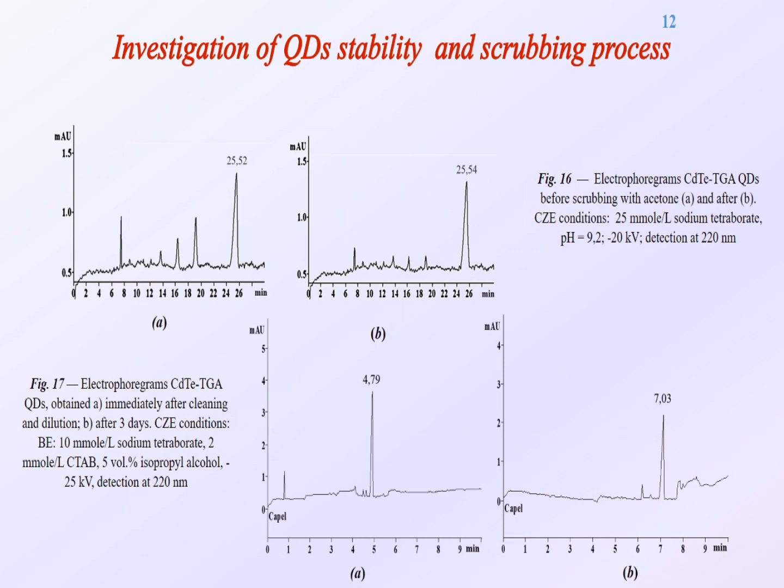Capillary electrophoresis was used to study the efficiency of quantum dots cleaning and their stability. The electrophoregram shows a decrease in the intensity of the peaks of impurity compounds, which we observed after purification, which indicates the effectiveness of this procedure.